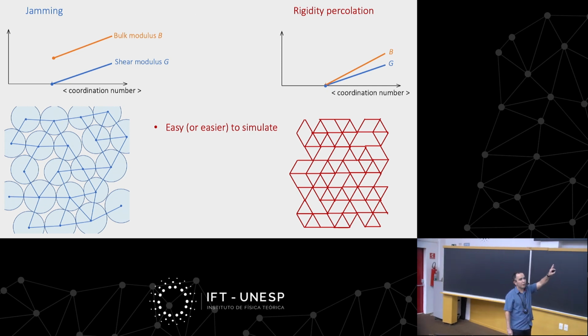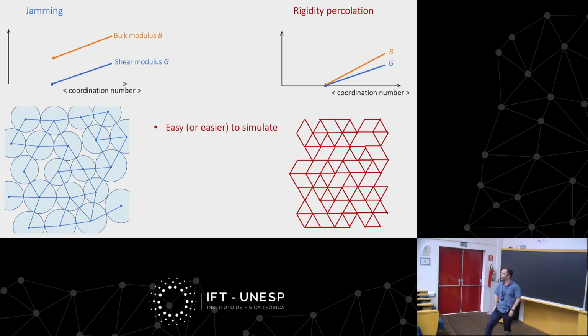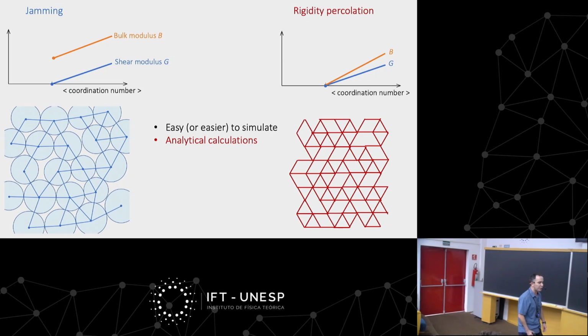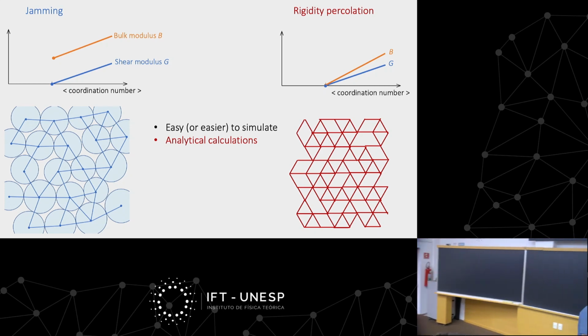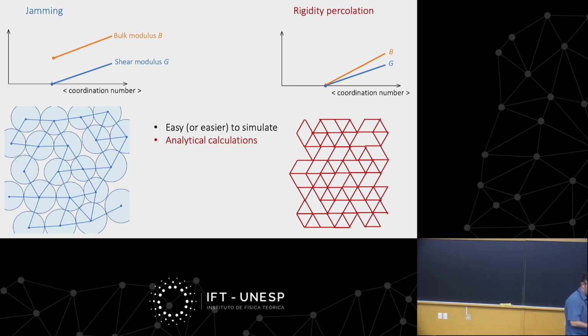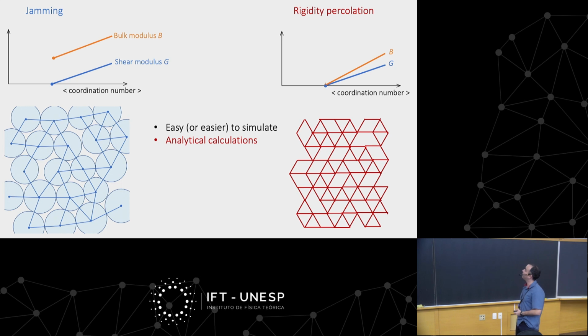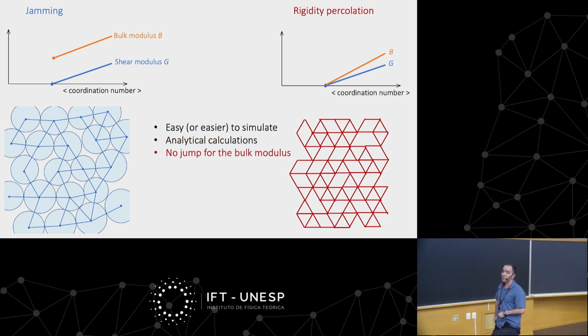Now, I like this kind of model, this rigidity percolation model, for several reasons. One of the reasons is that they are easy, or if they're not easy, they are at least easier to simulate. They are amenable to analytical calculations, and there are some approximations that I'm going to explore that make it very simple to extract analytical information about these systems, even for this disordered network that I'm showing here. But then, unlike the jamming transition, they don't show a jump for the bulk modulus. So that's something that's kind of different.